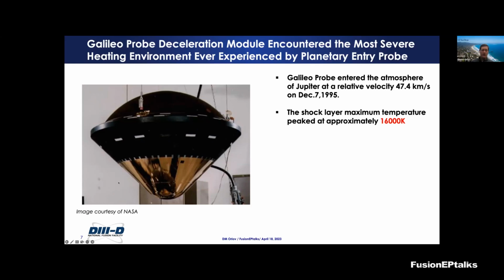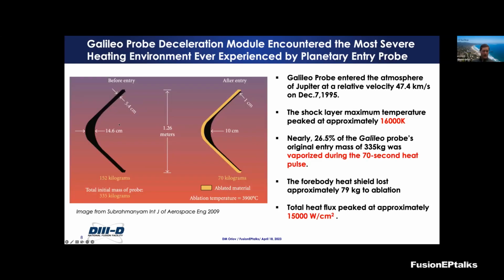If you see this image on the left, this is the Galileo's probe, and this is the thermal protection shield. The tip at the bottom is the front, where it was entering the Jupiter's atmosphere going down. All the instrumentation in the probe was hidden behind this thermal shield. The image here shows the shape of the thermal shield, with the nose being here on the left and the back sides covering the instrumentation. The shield was about 152 kilograms, and the total mass of the probe initially was 335. So that was a lot of the total mass that was sent to Jupiter.